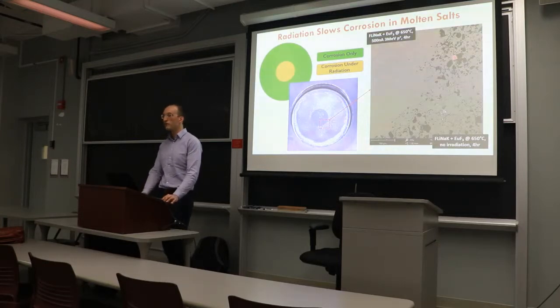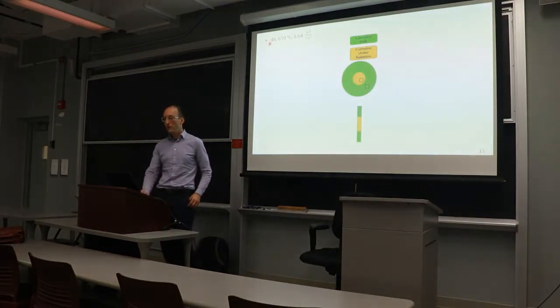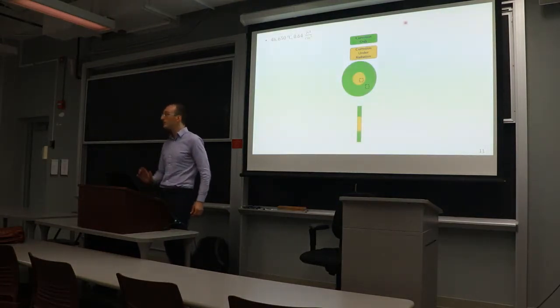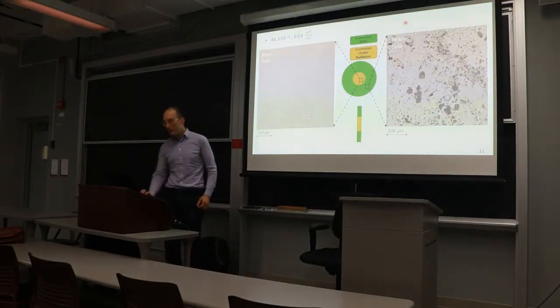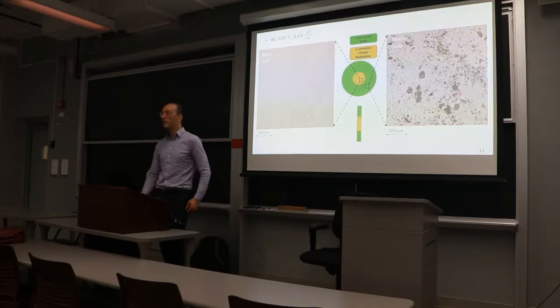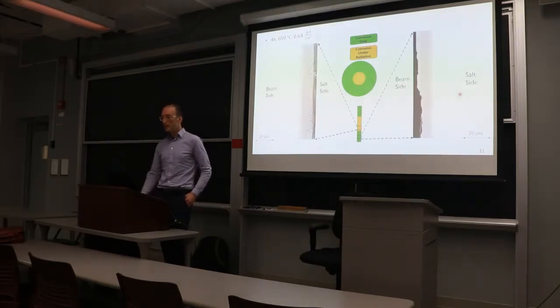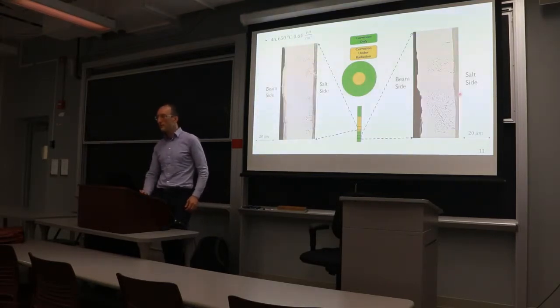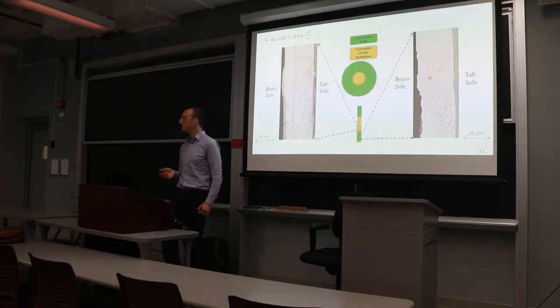And I'll show you a few images from different proton beam currents, all at 4 hours at 650 Celsius in the same FLiNaK and europium fluoride. When you look at the surface, the irradiated region is clean. If you look at a cross-section, to get a little more quantitative, you can actually see very orientation-dependent corrosion that only penetrated about halfway through on the irradiated region and made it all the way through in the unirradiated region. So we think there's about a factor of 2 slowdown at these conditions, which is awesome, right?